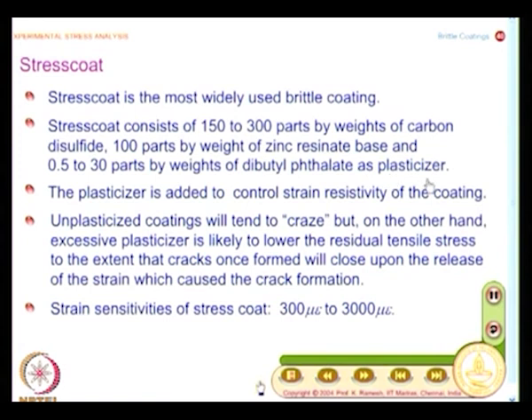The plasticizer is very important, and you need to handle it very carefully. The plasticizer does the job of controlling the strain sensitivity of the coating. If you do not plasticize the coating, the coating will tend to craze, that means spurious crack patterns will get formed. So, you need some plasticizer to be added. If you add excessive plasticizer, the cracks once formed will close upon the release of the strain which caused the crack formation. So, you have to add it very carefully. You cannot remove it completely, you need a minimum quantity, and what is the minimum quantity?